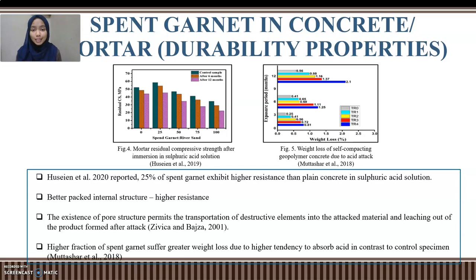The lower resistance of the concrete and mortar is due to the existence of pore structure that permits the transportation of destructive element into the attacked material and will leach out the product formed after attack. The higher fraction of spent garnet will suffer greater weight loss due to the higher tendency to absorb acid in contrast to the control specimen, reported by Muttashar et al., 2018